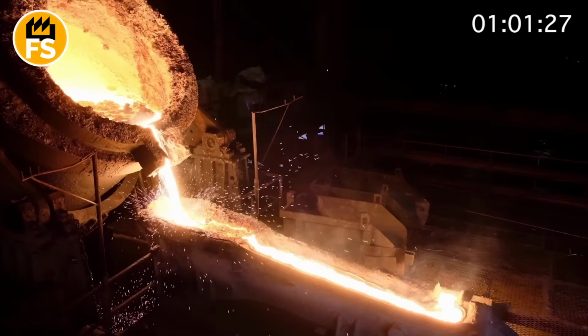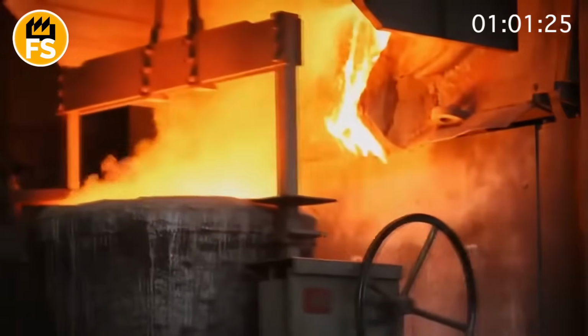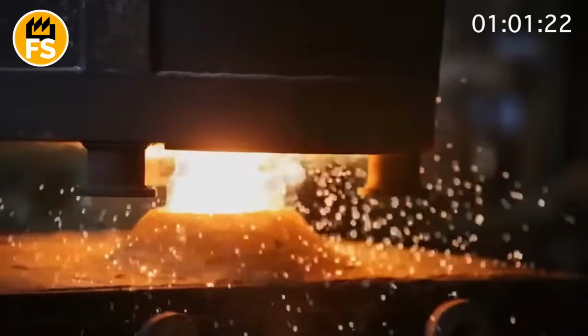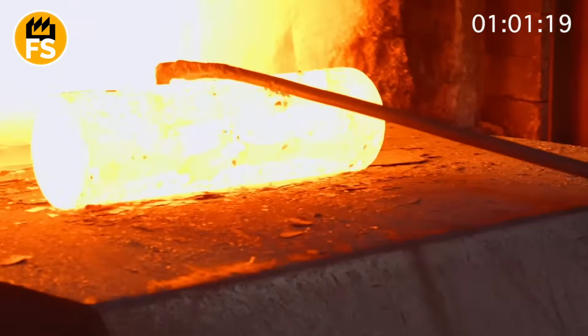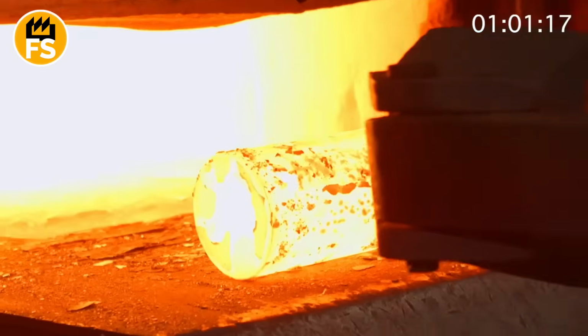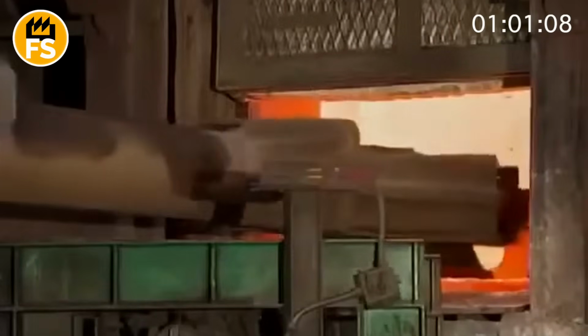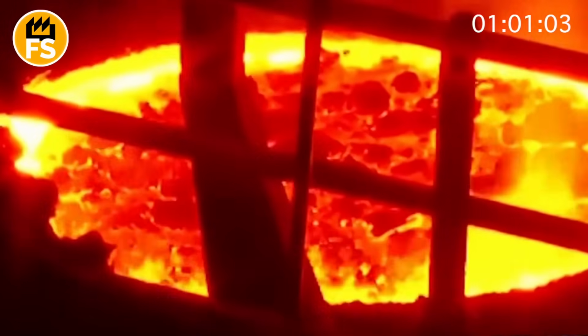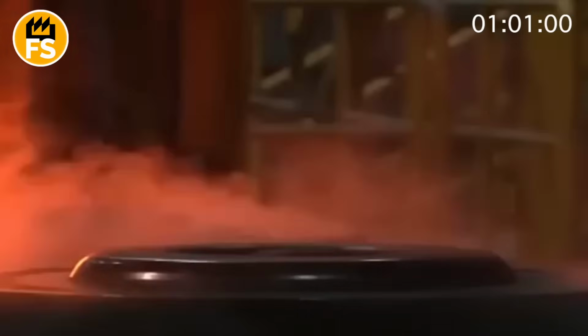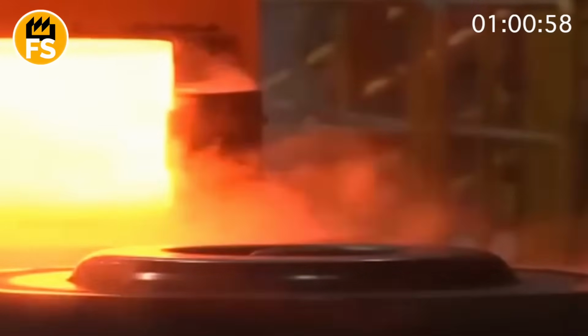Now begins the stage where brute force transforms the blank into a refined engineering product. The blank is heated again in a furnace to a plastic state, approximately 2,250 degrees Fahrenheit, and sent under a press. This is a hydraulic machine with a force of 4,000 tons. The forging process takes place in several stages. First, the press upsets the blank, making it shorter and wider. Then it is moved to the first die, which begins to form the main elements: the rim, the plate, and the hub. The next step, a powerful punch pierces a hole in the center for the future axle.